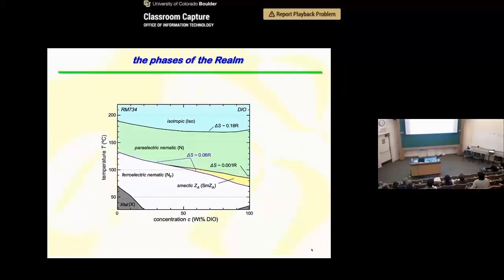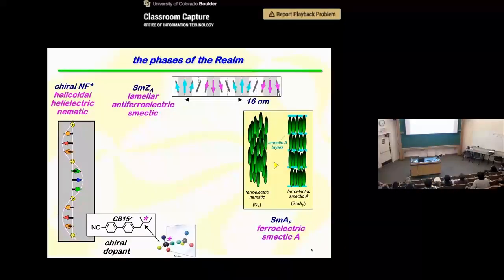Okay, so then we started out with these two phases, the ferroelectric nematic, and then this extra phase that's in DIO. Okay, so we either discovered or structurally characterized the first six phases of the ferroelectric nematic realm. And so you can take the ferroelectric nematic and add chiral dopant.